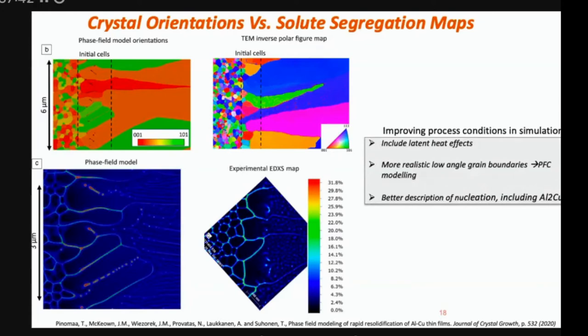And so more work is being done to understand. We think that at this point, not only is non-equilibrium effect of solute partitioning relevant, but you also have to bring back temperature dependence dynamically, because that should be a rate-limiting step in terms of say latent heat and its subsequent diffusion. That's why probably the experiments have shorter initial grain elongation than the theory. Because in our theory, we kind of freeze in temperature at every time, but the temperature should probably be now brought back to the game as a dynamical barrier.